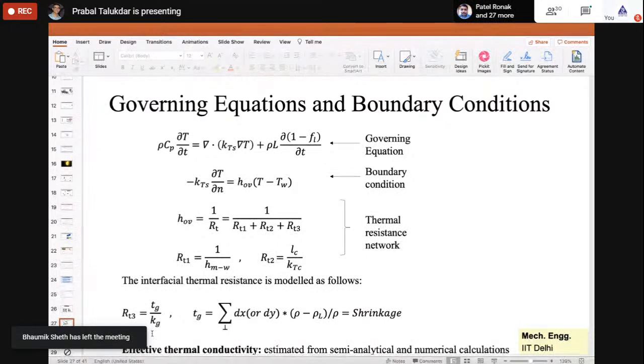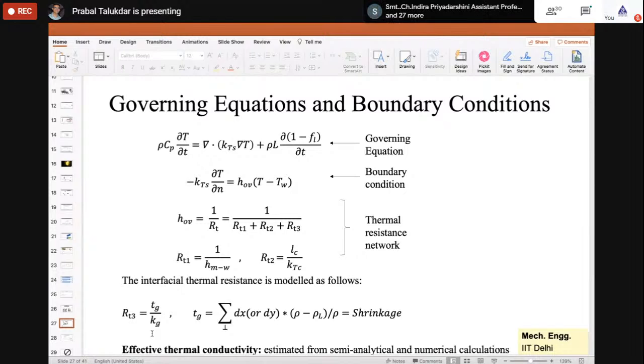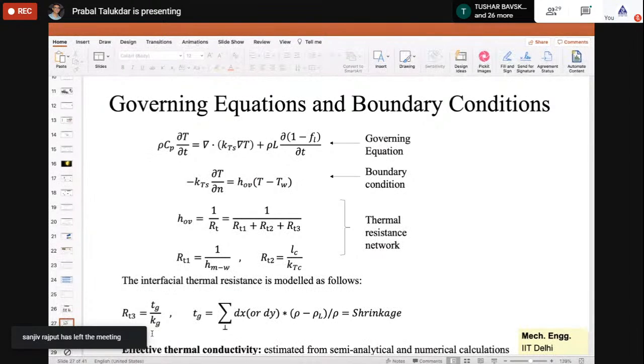The only unknown is basically this Kg, which is the conductivity of the air. Now the conductivity of air is known to us for sure, but the problem is that it is not really air. Inside that air gap there are gases which form because of whatever additives are added in between the slab and the mold. Some oils are added there so that the billet doesn't stick to the mold. Because of that, at high temperature, the oil evaporates and cracks, forming certain gases, so it's not just air, and this Kg is slightly different from air conductivity.